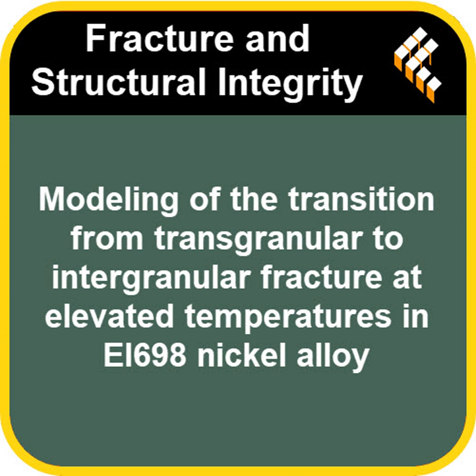Exactly. And what's fascinating here, and a key observation in these types of alloys, is a surprising shift. As the temperature climbs, the failure mechanism actually changes. It moves from being predominantly transgranular cracking at lower temperatures to intergranular cracking at higher ones. Ah, so the heat changes the path the crack prefers. Precisely. And this shift is incredibly hard to model accurately.